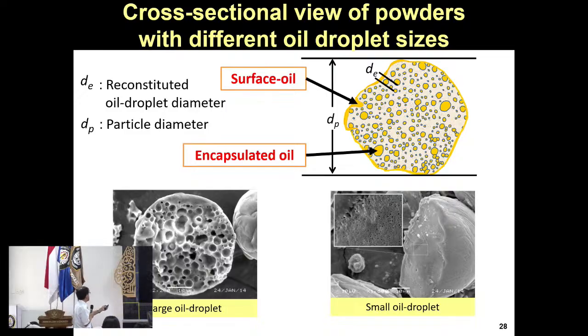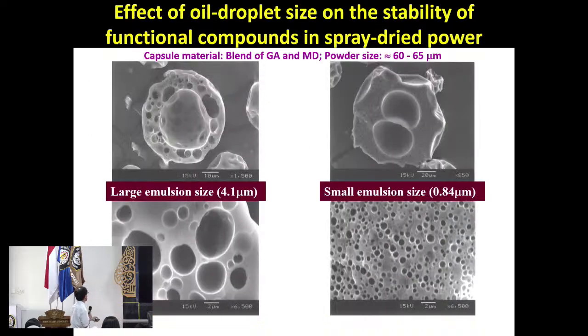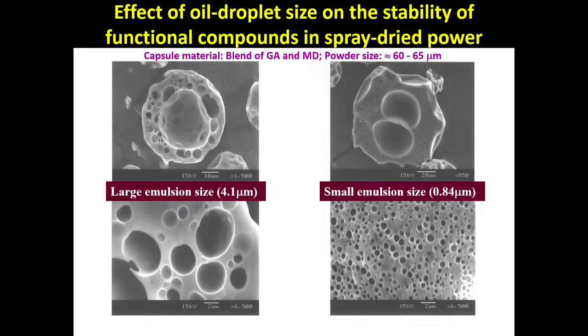And then when we make a larger oil droplet, 3 micrometers, 4 micrometers, the oil is not encapsulated in the raw material. So the oil droplet size is important. Surface oil means the not encapsulated oil. For example, this is a large emulsion, 4 micrometers, and this is 0.84 micrometers.